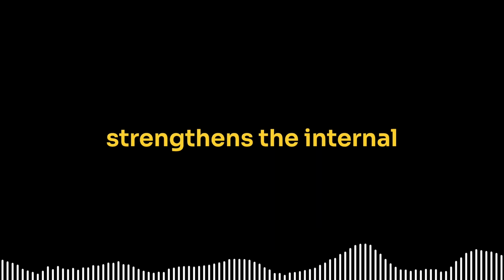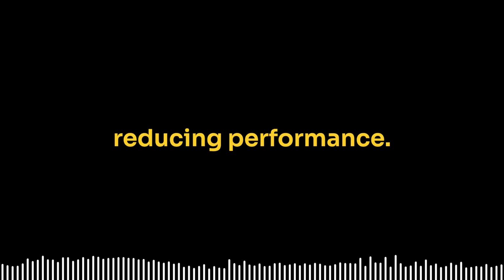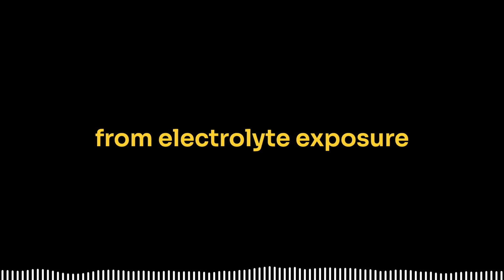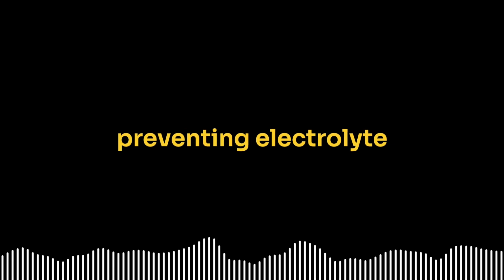However, while doping strengthens the internal structure, LCO's surface also needs protection, which is where coatings come in. LCO is in direct contact with the liquid electrolyte, and over time, unwanted side reactions at the surface can form a thin, resistive film, slowing down lithium-ion movement and reducing performance. To prevent this, manufacturers apply ultra-thin protective coatings that shield LCO from electrolyte exposure while still allowing lithium ions to move freely. Aluminum oxide forms a stable surface barrier, preventing electrolyte degradation and extending battery life.